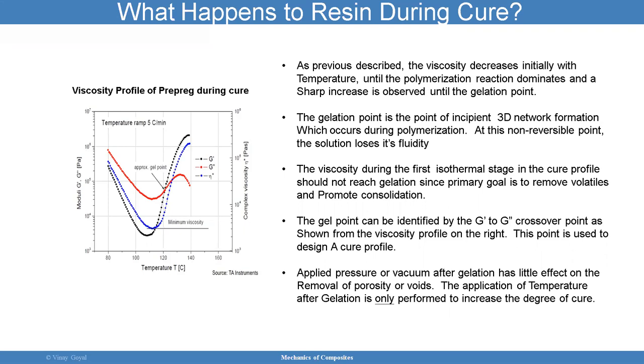Applied pressure or vacuum after gelation has little effect on the removal of voids. My point being, once you pass the point of gelation, you have very little ability to remove voids. That's why you have to remove voids and consolidate by decreasing viscosity with the initial temperatures, and you want to do that to get the polymers to react. Once you get that going, then you can get into gelation, the point at which you have full or some polymerization. At this point you have non-reversible behavior. So the application of temperature after gelation is only performed to increase the degree of cure, to promote the ability to get a final product that's fully cured as much as possible.